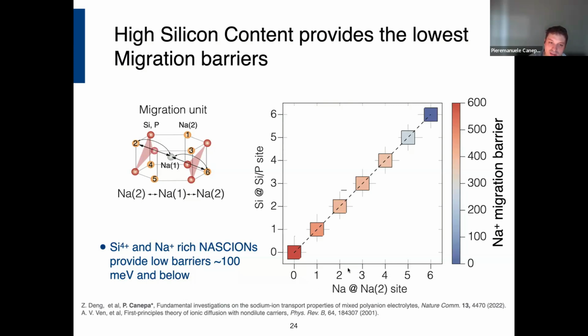What I'm changing on the x-axis is basically whether these orange balls are vacancy or occupied lattice sites. When you see 0 here, it means that the balls are all vacancies, and when you see 6, all six are occupied by sodium. Likewise, I can do the same thing with the silicon phosphorus ratio. Where you see 0 here, it means that all the red balls are occupied by phosphate, and at 6, all the red balls are occupied by SiO4 units. Now we plot how the migration barriers evolve as we move from 0 sodium on the sodium 2 lattice and all phosphorus. This is a terrible barrier, above 600 milli-electron volts, I apologize, the units are electron volts. And this is well aligned with experimental estimation of migration barrier at this sodium composition.